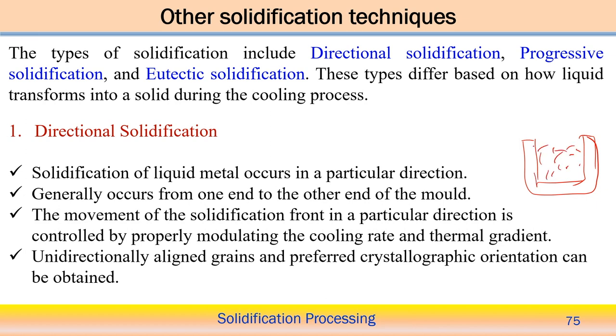It is expected, and normally we have observed, that solidification starts from the wall and then gradually moves toward the center. Depending upon the parameters, in whichever direction the temperature gradient is the maximum, nucleation occurs and grain growth occurs in that direction. So, this kind of solidification is basically not directional solidification, because it is not moving in one particular direction. It is moving randomly, without any specific direction. That is why it is not directional solidification.